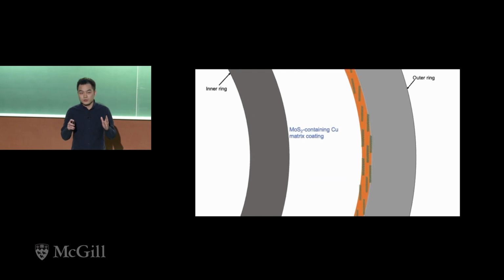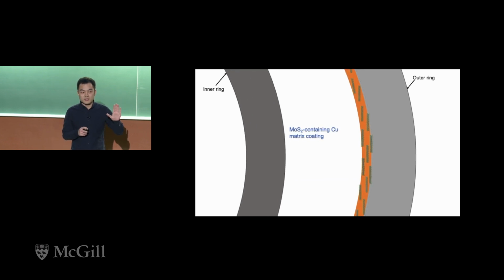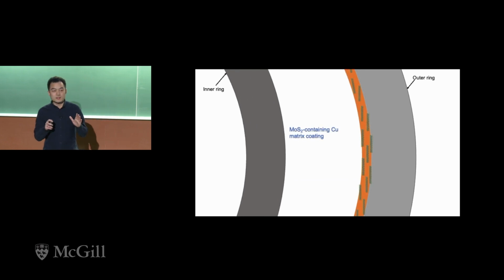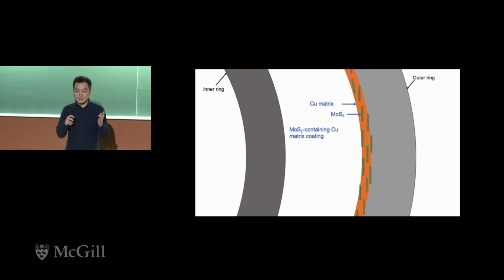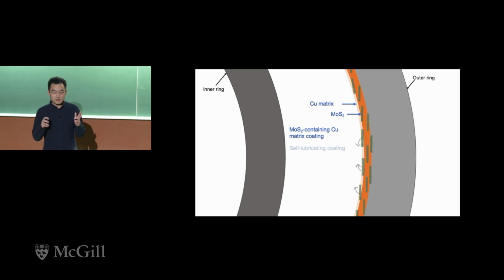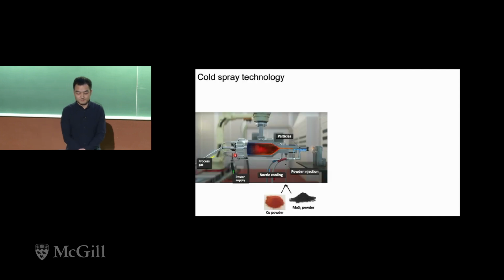What we are going to do is to produce a coating on the contact surface, not an entire MoS2 coating since it is easily worn away, but a MoS2-containing copper matrix coating, which mainly consists of very resistant copper, but also has MoS2 inside. In that case, MoS2 can be replenished to the contact region all the time, even if part of the coating is worn away. That's why we also call it self-lubricating coating.